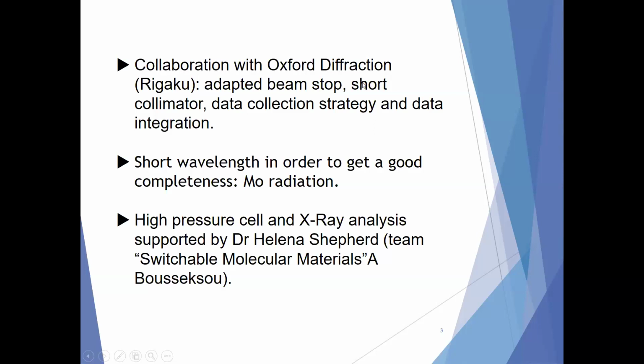So it was made with an adapted beam stop with short collimator. And already, even in 2010, CrysAlisPro and CrysAlisRed made easier the data collection strategy and the data integration for high-pressure data. For high-pressure studies, it is recommended to use short wavelength, silver or moly, to get good completeness. And so on the Gemini, when we carried out these experiments, we used, of course, the molybdenum tube.